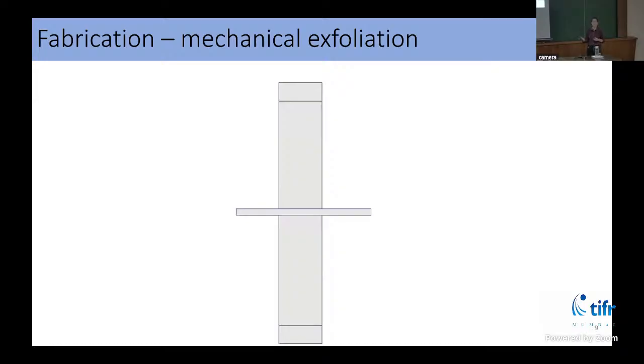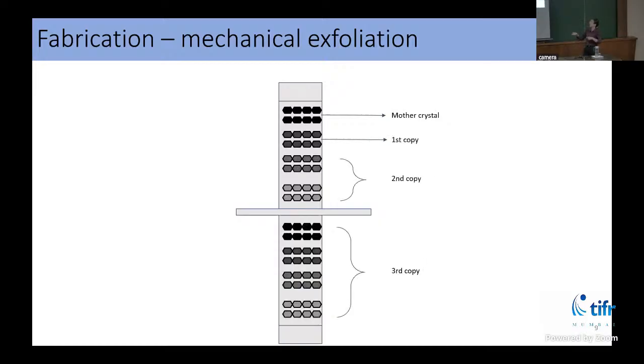Yeah. So next I want to describe how we make these devices in our lab. The first step is to get the graphene that we want to work with, the flakes, and that's the main ingredient of our devices. What we start with is mechanical exfoliation. We take a tape, known as Scotch tape, and we take some amount of bulk graphite crystal on it. The process of mechanical exfoliation is that I stick this tape on top of it and then peel it again. In doing so, I make multiple copies of that crystal on the tape.